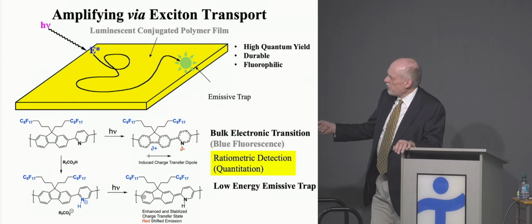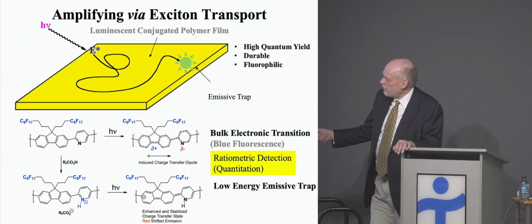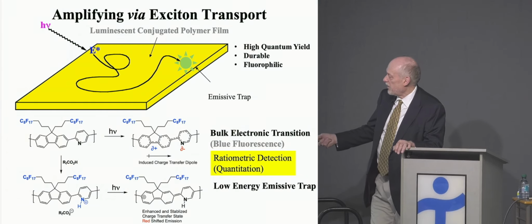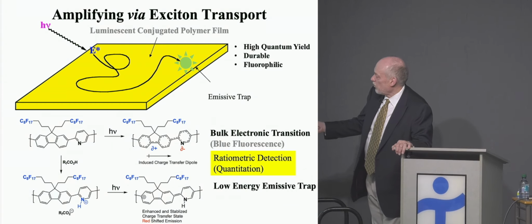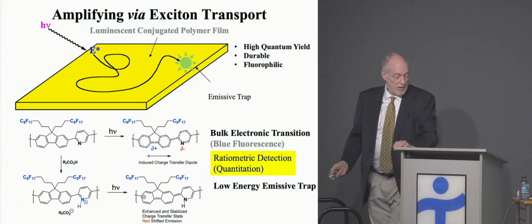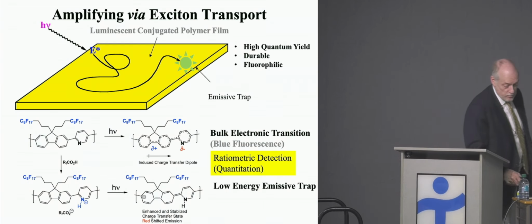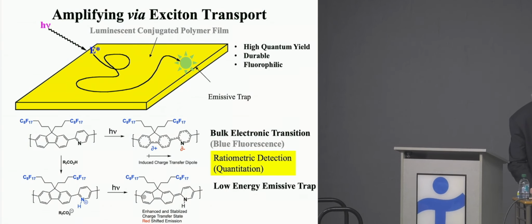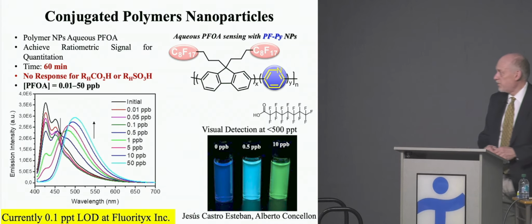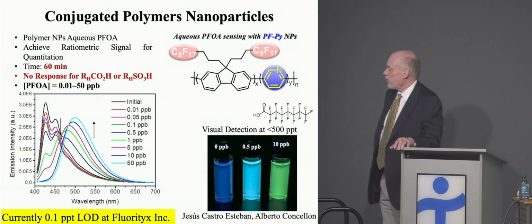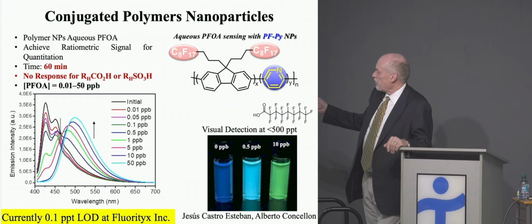And that's a smaller dipole, but if I absorb PFAS into this, the PFAS tends to have a proton that will make this nitrogen positively charged. So this becomes more favorable to basically kick the charge this direction. You get a very strong dipole. So this is blue fluorescent, and this becomes green. And so we have done this on different films, on different forms. This is on a particle form, showing you how this works.